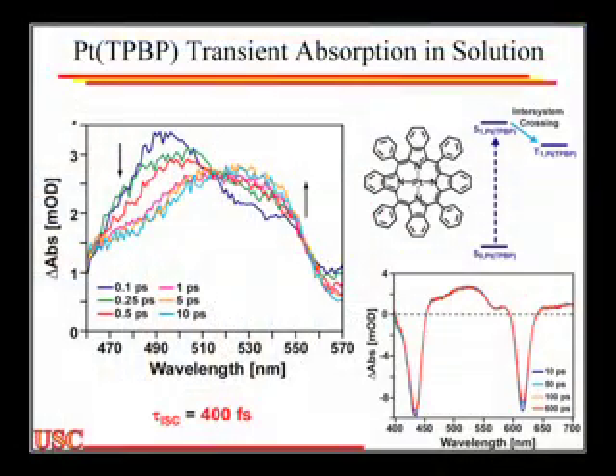So let's take the simplest one, the tetrabenzoporphyrin compound. I put this in solution, so it's in an inert matrix. It's in THF or methylene chloride, I can't remember which solvent it was in. And I pump it, I believe this was pumping into the Q band, but I don't remember. I think it was pumping at 600 nanometers, but it doesn't matter. Within about 1/10 of a picosecond, you can see I've got my bleach. There's my Soret band and my Q band that are bleached. And I've built in an absorption that wasn't present before.